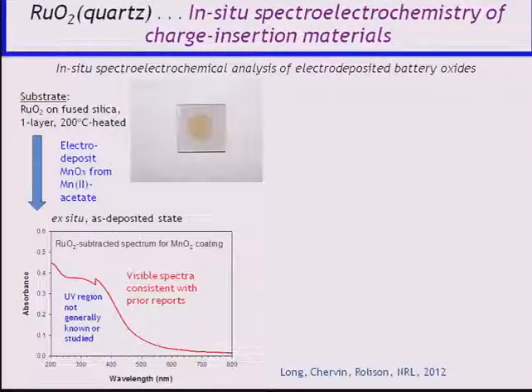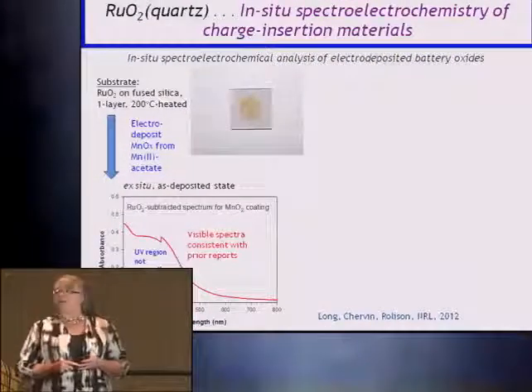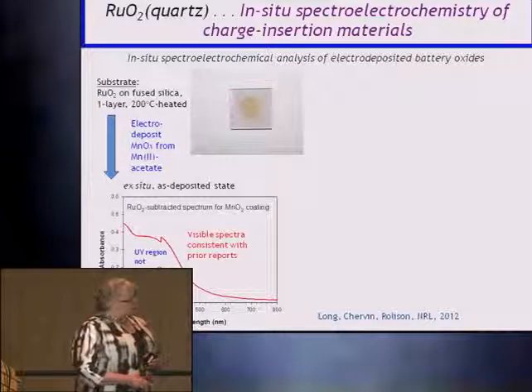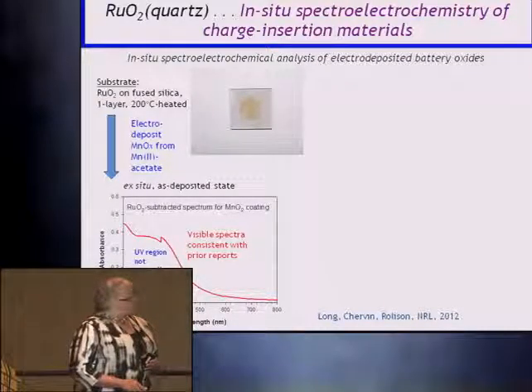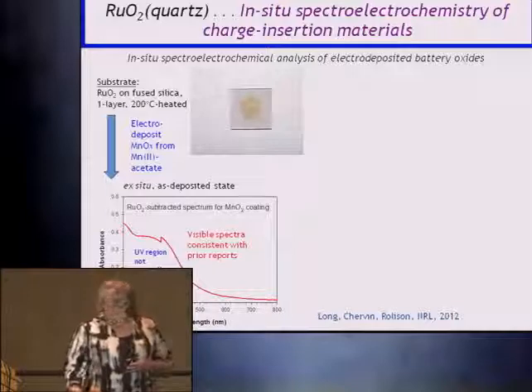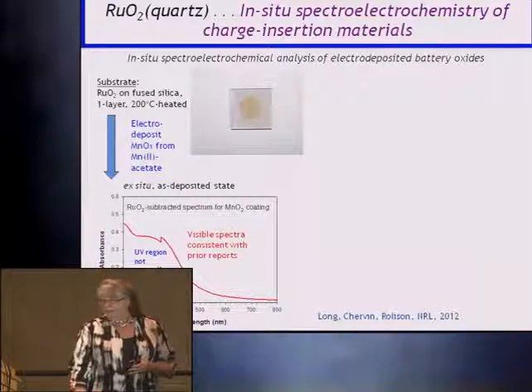So in this example, Jeff Long took the ruthenia deposited on fused silica, so that's the window, electrodeposited electrolytic MnO2, which is what's running this laser pointer, and then took an in situ spectrum, subtracted the background, and you can see there's information in the ultraviolet. And this is a region you just generally don't and can't study with these metal oxides. It's known to be more colored when it's manganese 4, and it decolorizes as you reduce it to form manganese 3, and the lithium or other cation would insert into the structure.